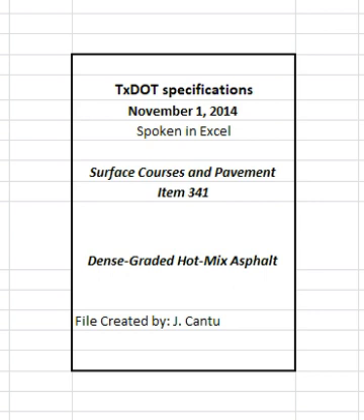2.6.1 Lime and liquid anti-stripping agent. When lime or a liquid anti-stripping agent is used, add in accordance with Item 301, Asphalt Anti-Stripping Agents. Do not add lime directly into the mixing drum of any plant where lime is removed through the exhaust stream unless the plant has a baghouse or dust collection system that reintroduces the lime into the drum.